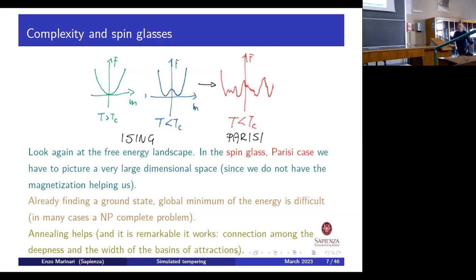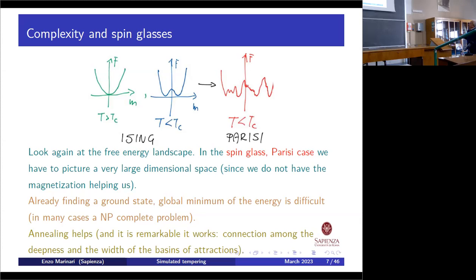And now this is the same picture as before. Typically, this is a Parisi picture, right? A lot of barriers, multiple equilibria, so there are many stable states or even very, very slow decaying metastable states. This picture should be in 10 to the 23 dimensions, because we don't have the presence of a magnetization, right? And so we should look at it.